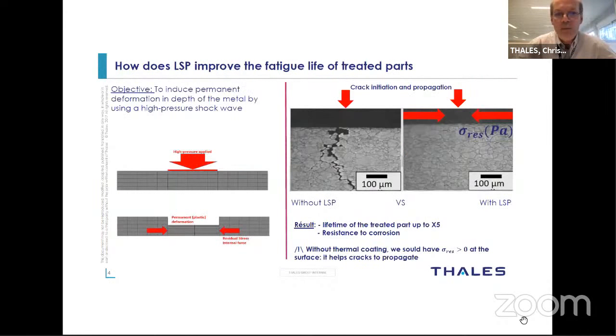To give you an example of what the real effect is, you can see the 2 pictures on the right. You see the picture quite in the middle. You see what happens if there is a crack, for example, a corrosion crack initiating and propagating within the material. And on the far right, you see what happens if you have applied the laser shock peening process. So you see that you can avoid or limit the propagation of the crack.